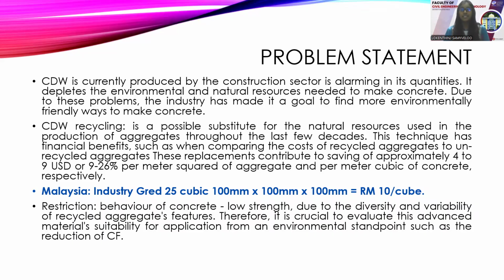concrete. Second, CDW recycling is a possible substitute for the natural resources used in the production of aggregate throughout the last few decades. This technique has financial benefits, such as when comparing the cost of recycled aggregates to unrecycled aggregates, these replacements contribute to savings of approximately 4 to 9 USD and 9 to 26 percent per square meter of aggregates and per cubic meter of concrete, respectively. As we all know, the Malaysian industry uses grade 25 cubes, the size being 100 mm by 100 mm by 100 mm, and RM 10 ringgit is contributed per cube.